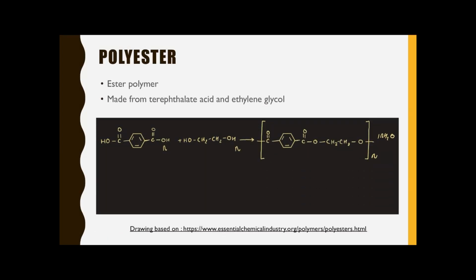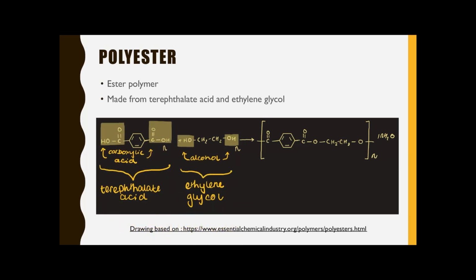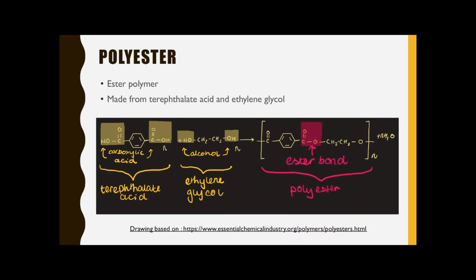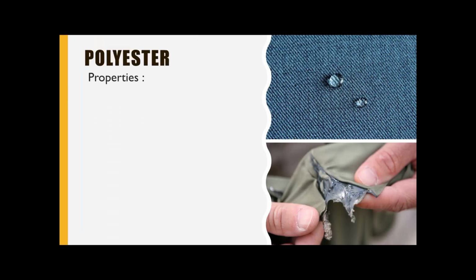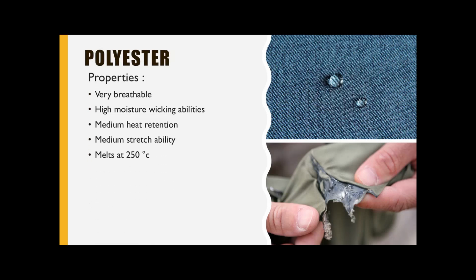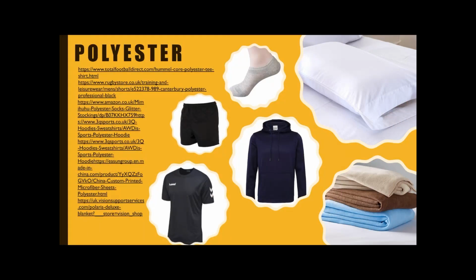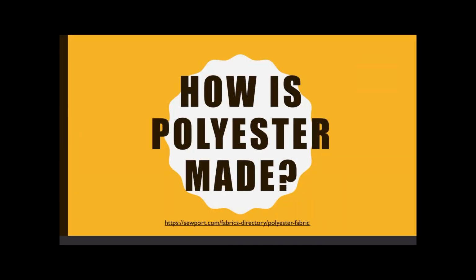Polyester is an ester polymer. It's made from terephthalic acid and ethylene glycol. As you can see, it's a carboxylic acid reacting with an alcohol, forming an ester bond. Polyester is very breathable, has high moisture wicking abilities, has medium heat retention, medium stretchability, melts at 250 degrees Celsius, has little friction, and a high luster. Polyester can be used to make shirts, hoodies, shorts, socks, sheets, blankets, and quite a few other things, as it's usually blended. How is polyester made?